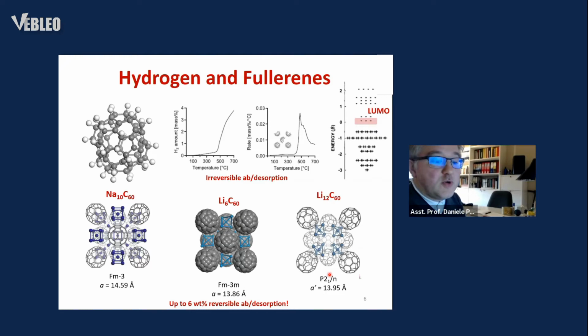And for example, it is well known that C60 can form the so-called alkali intercalated fullerides, which are actually charge transfer salts, where the alkali ions donate an electron to the fullerene molecules, thus populating the LUMO band and negatively charging the cage.